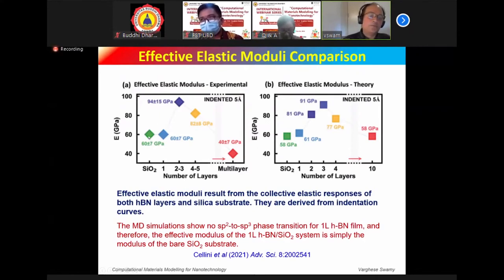You can see that when it's silica, it's about 60 GPa. And if you have one layer, it's essentially the same. That means we are measuring the elastic modulus of the silica substrate. But when you put 2 to 3 layers, the elastic modulus jumps up to 94 GPa. That means that there is this SP3 bond layer forming, which is much harder to compress. So the elastic modulus goes up. But when you increase the number of layers beyond that, because of the stress situation under the indenter, it's not transmitted completely and it's not really forming a lot of layers at the top. And that's what happens with the increased layering.